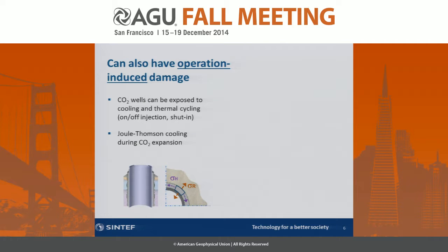And then, of course, the casing will expand and contract more if this is repeated several times, so it cycles, than the surrounding cement and rock. And this can be very damaging to the well. You can have these tensile radial stresses or tensile hoop stresses that can cause debonding or radial cracking in the well.